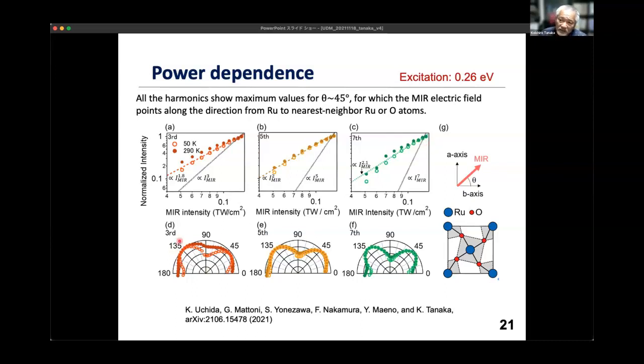And we also obtain very nice crystal angle dependence. This 45 degree corresponds to the ruthenium oxide bonding direction. We know such a charge transfer excitation exists around 1 electron volt, so this resonance is contributing to the high harmonic generation. This is very similar to the conventional semiconductor. Bonding information is obtained.